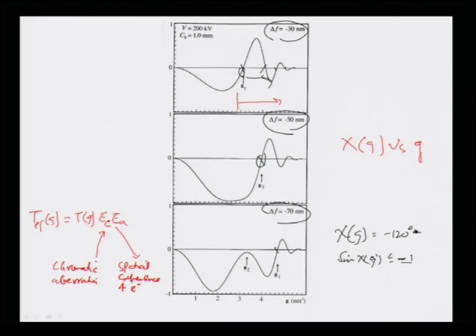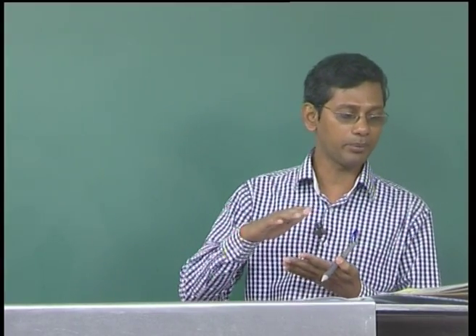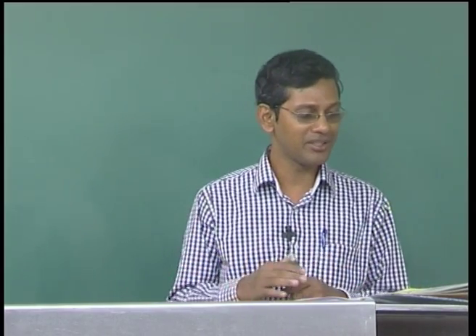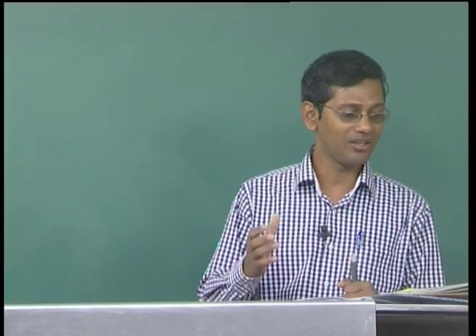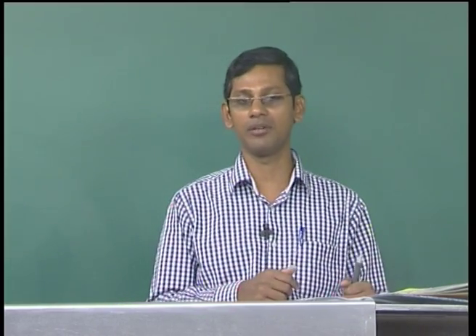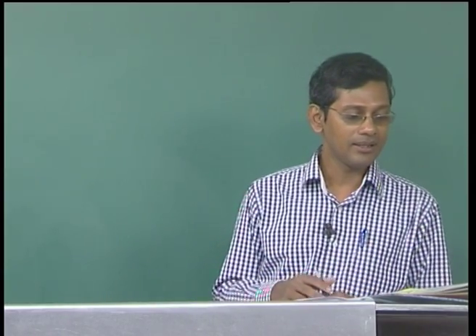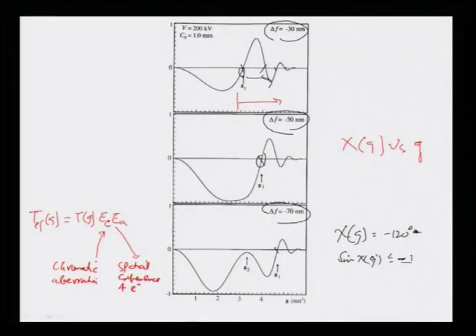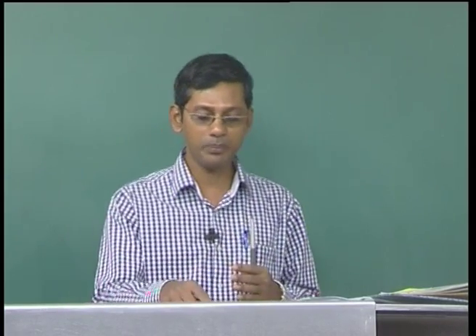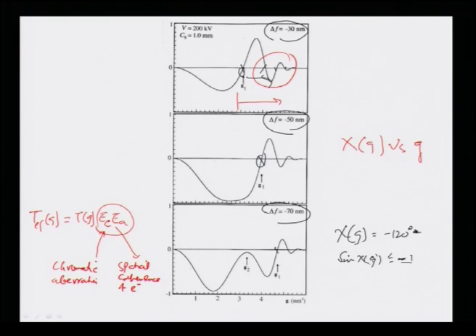So that means physically, if we at all put an aperture in the back focal plane to remove this unwanted noise, it must be smaller than the virtual aperture present because of these envelope functions. The presence of this virtual aperture means the higher order pass bands, the higher order values, are never accessible. They cannot be accessed because of the presence of these envelopes. That's why I say these are envelope damping functions; these frequencies are getting damped out because of the envelopes due to chromatic aberration and spatial coherency.